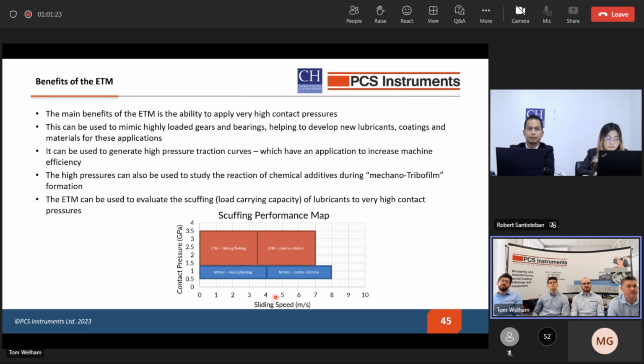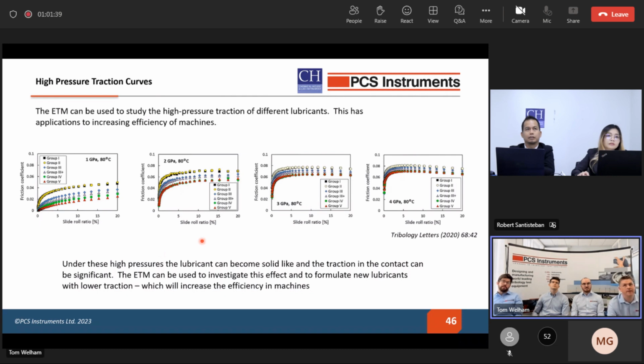Just as an example of the scuffing here, we can see the range that the ETM gives us in terms of contact pressures and speed when we're looking at scuffing, as compared to the NTM. Traction curves are made in the same way on the ETM as the NTM. The graphs here on the left show 4 traction curves at different contact pressures from 1 to 4 gigapascals. This is from a paper in Tribology Letters.